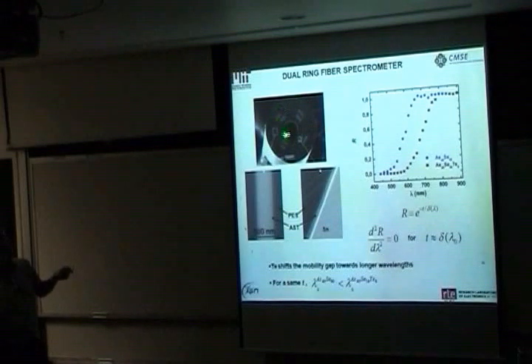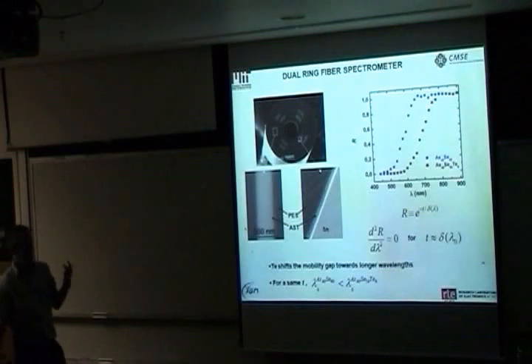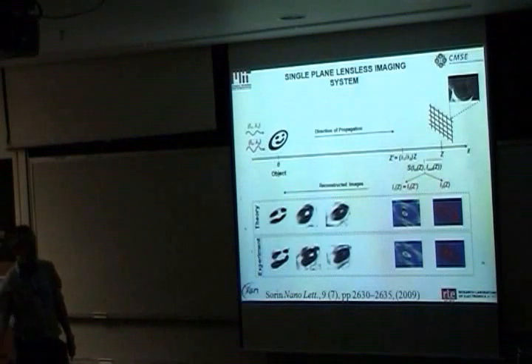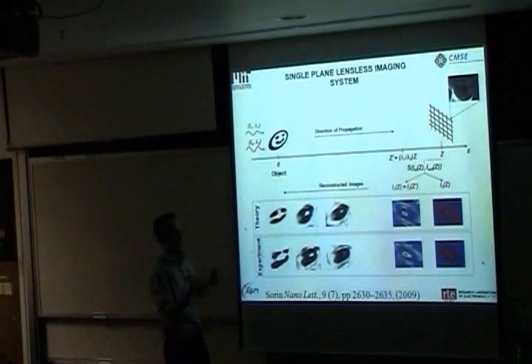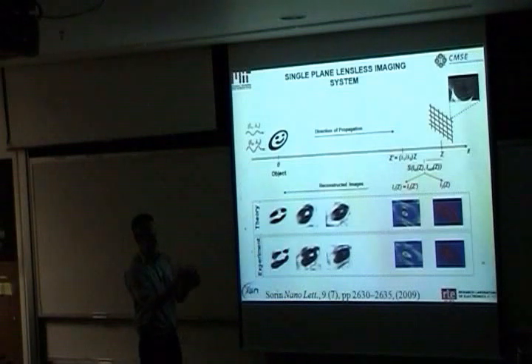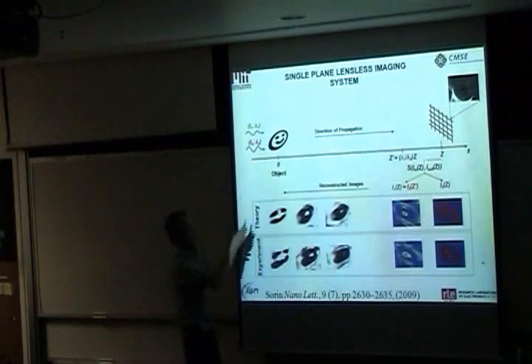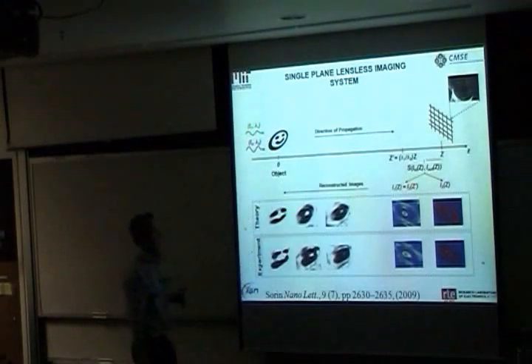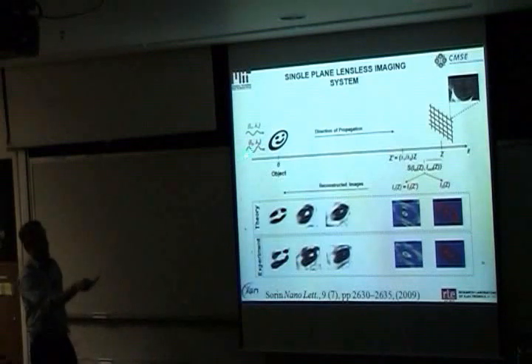Basically, we showed here that the design of the fiber with these 8 electrodes actually gives you a tuning curve that allows you to, in fact, measure the wavelength of illumination. And if you have polychromatic illumination at 2 wavelengths, you could actually discern the intensity associated with each of these. And if you go back to the Fresnel transform, what you immediately see there is that distance in the Fresnel transform and wavelength actually come about as a product. And so you could either use 2 different planes, or you could actually use 2 different wavelengths. And so here, we took an object and we illuminated it with 2 wavelengths simultaneously, so with polychromatic illumination.